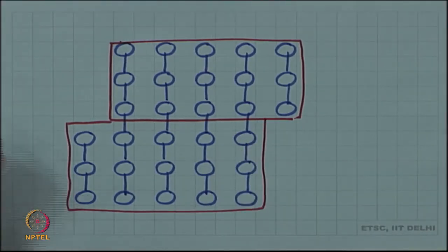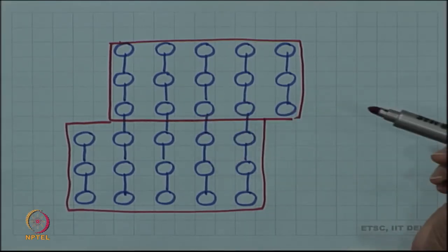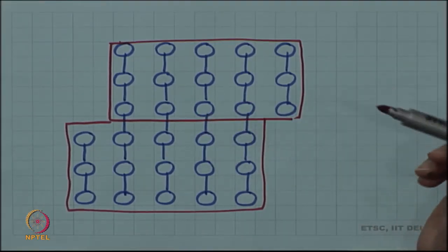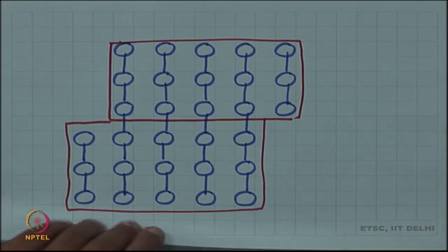However, it was achieved in steps such that in each step we were breaking only one set of bonds, and that is why the required stress was much lower.